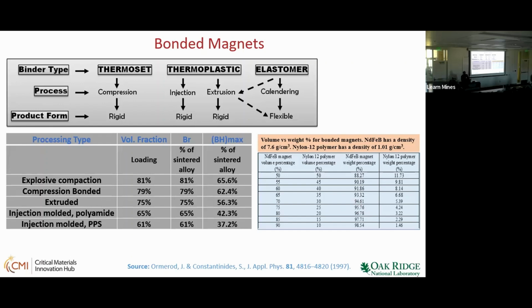So the volume is better, and the energy product is directly proportional to the square of the magnet volume fraction. So let's say you have 70 volume percent of a magnet. 70 volume percent corresponds to 95 grams. So 95 weight percent of magnet is 70 volume percent. So 0.7 squared. If the starting magnet powder is 40 MGOe equivalent powder, you will end up with 20 MGOe. So the starting magnet decides your bonded magnet. That's where the challenge is, how much loading you can do with this manufacturing process, and how far you can go.